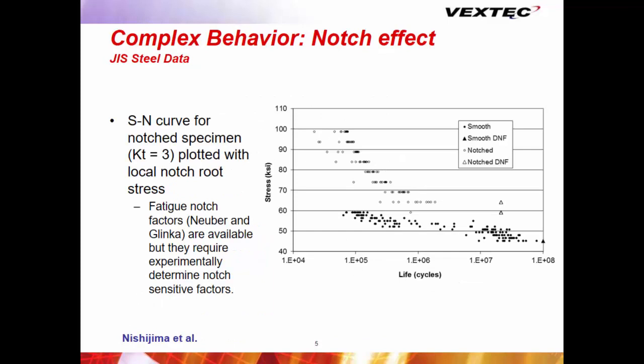So why should it change the fatigue strength when I put a notch in a bar? Well, because the fatigue strength is not a material property. I don't have an S-N curve for steel. I have an S-N curve for steel with a notch in it. If I change the notch size, I get another S-N curve.